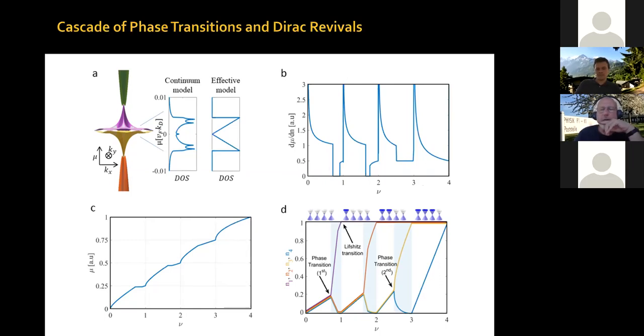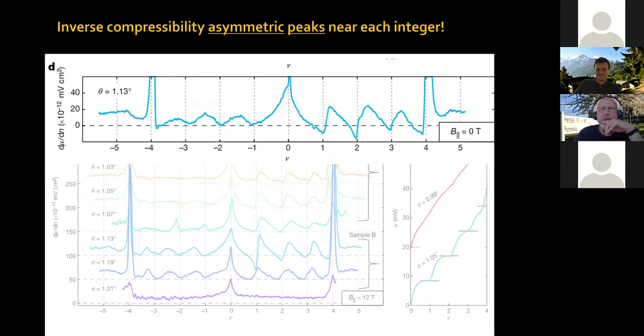And in this context, the curves that you have shown, the inverse compressibility, at some points it seemed to become negative. What does that mean? Very good, indeed. Let me just show this one, for example, right? You see that you have negative inverse compressibility. Obviously, you can no longer speak about single particle density of states in that case, right? You will not have a negative density of states. Negative inverse compressibility is something that is often seen when you have interactions. So for example, in the fractional quantum Hall regime, you see negative inverse compressibility.